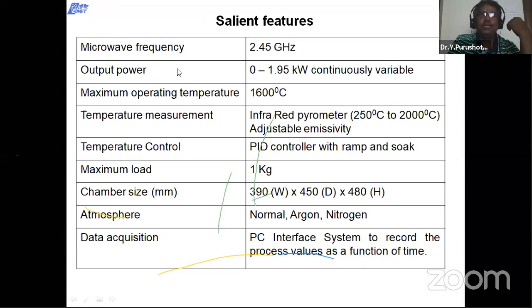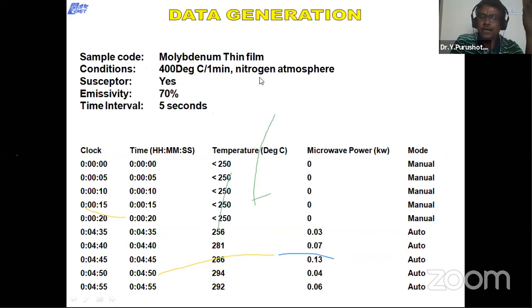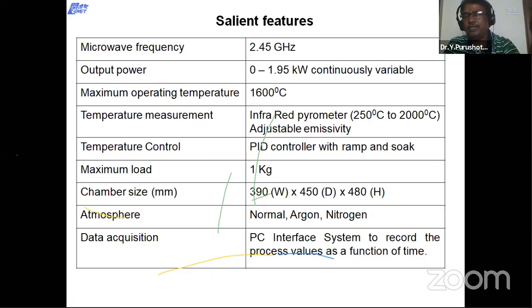And these are the salient features. The microwave frequency is 2.45 gigahertz. Depending upon the absorbability of the material, the microwave output power is continuously variable from 0 to 1.95 kilowatt, because this is a 2 kilowatt furnace. So it is continuously variable, not just on-off. If you see a domestic oven, whatever we are using, if you close the door, it will be 800 watts, and if you open, it will be 0. So either 800 or 0. But in our furnace, depending upon the microwave's penetration, the power will vary from 0 to 1.95 kilowatt.